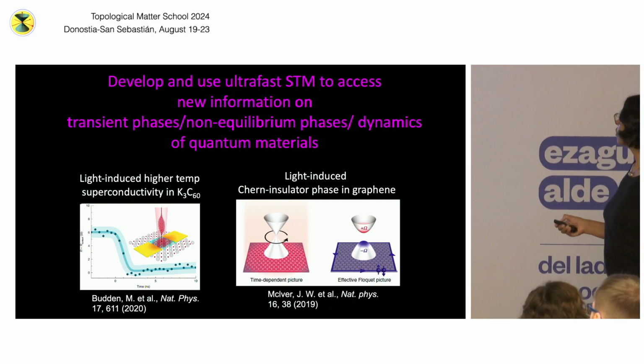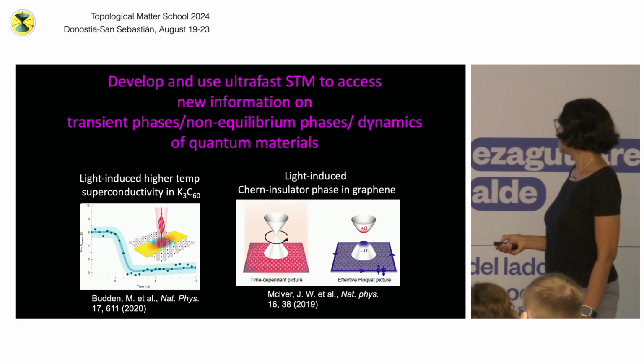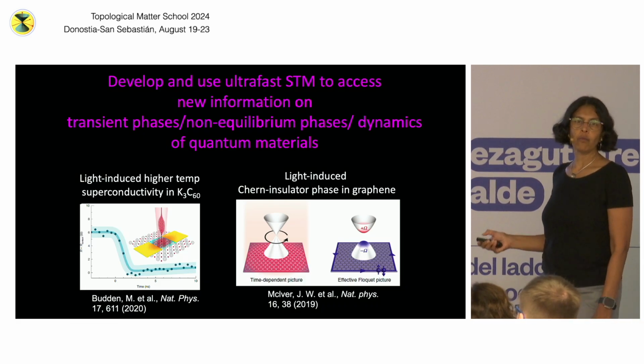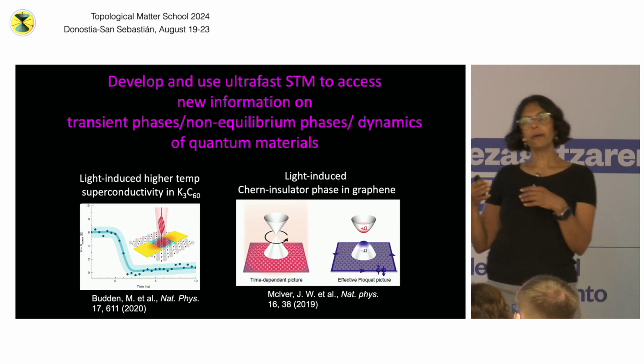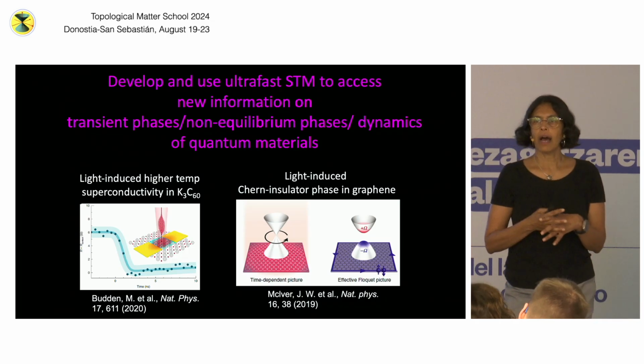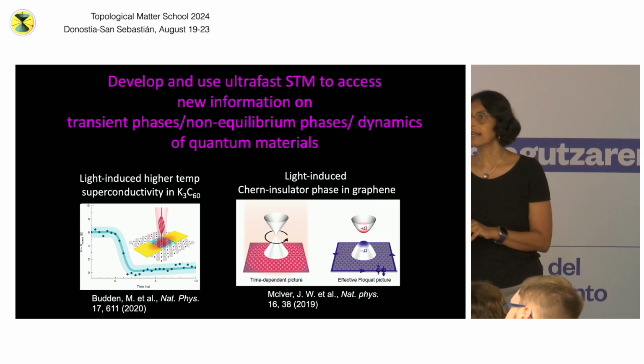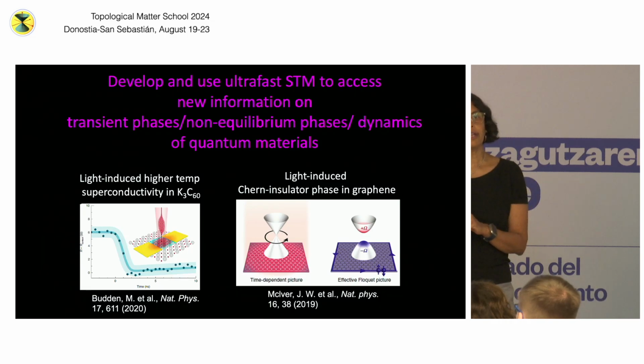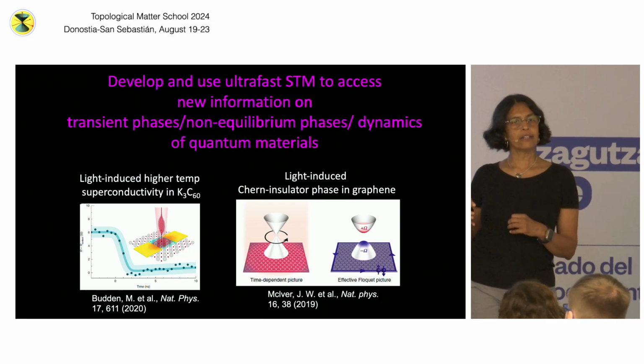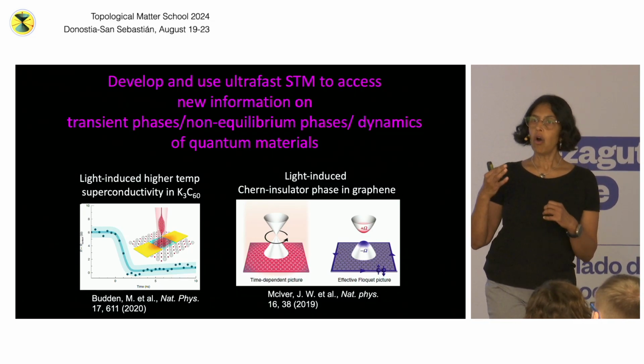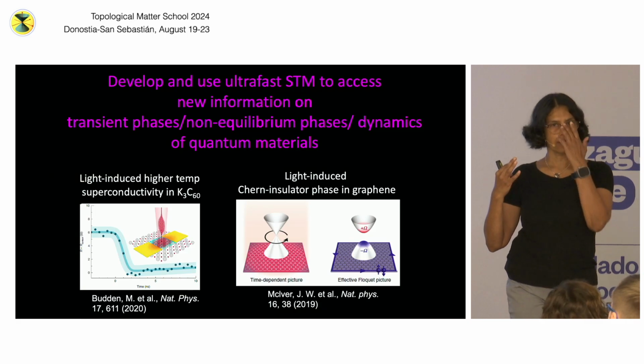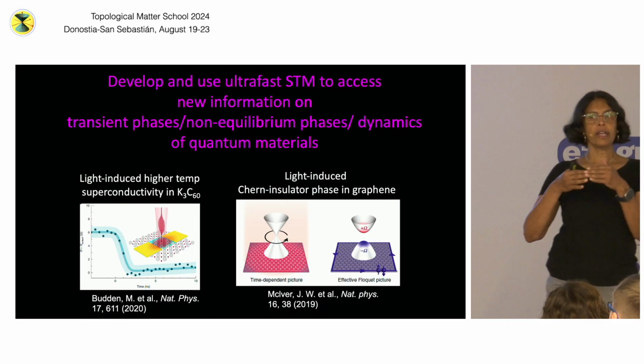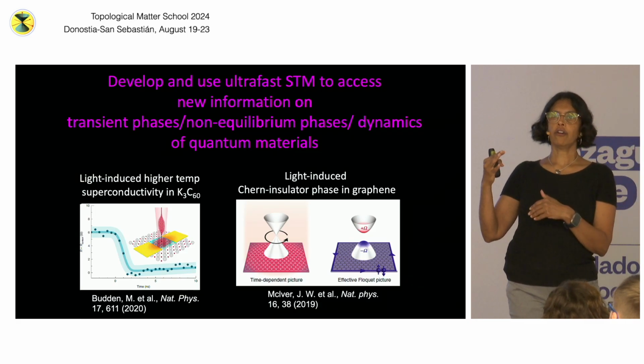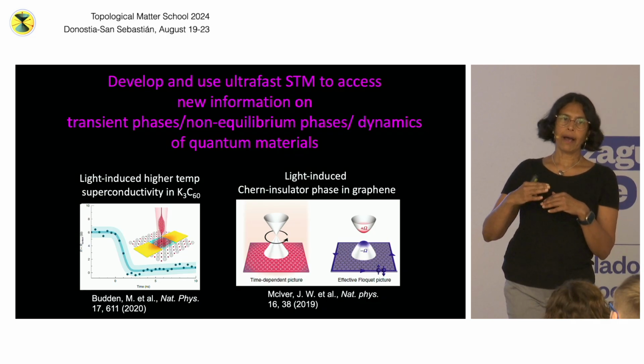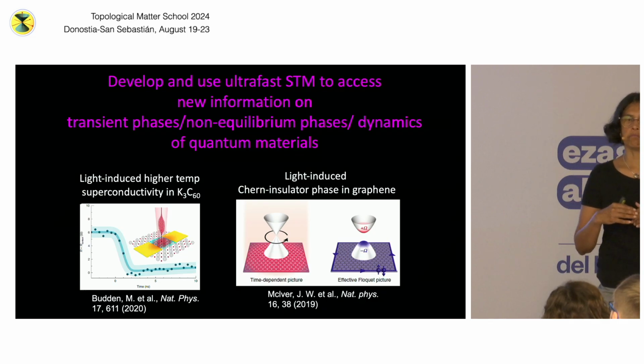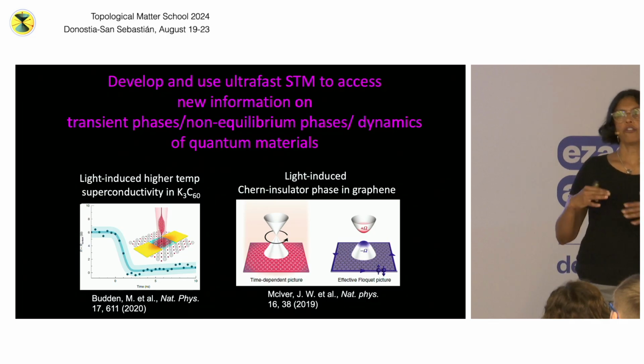So there are a couple of really cool experiments that have been done with shining light on superconductors. So Andrea Cavalleri's group, for example, has done a series of experiments where they show that if you shine pulse laser light on a superconductor, or even in a material that's non-superconducting sometimes, you can increase the transition temperature of the superconductor by quite a bit, sometimes even 100%.